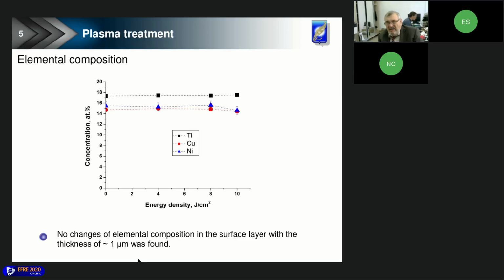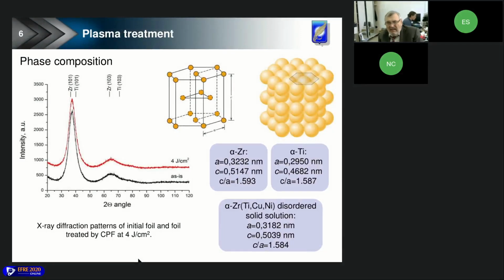Well, the X-ray diffraction data showed that the foil phase composition after CPF treatment was strongly dependent on the energy density absorbed by the surface layer. First, let us consider the initial sample. Two broad diffraction lines corresponding to a structure with short-range order are observed in the diffraction pattern of the initial foil. The angle position of these two diffraction lines was close to the angle position of low-temperature zirconium and low-temperature titanium standard diffraction lines.